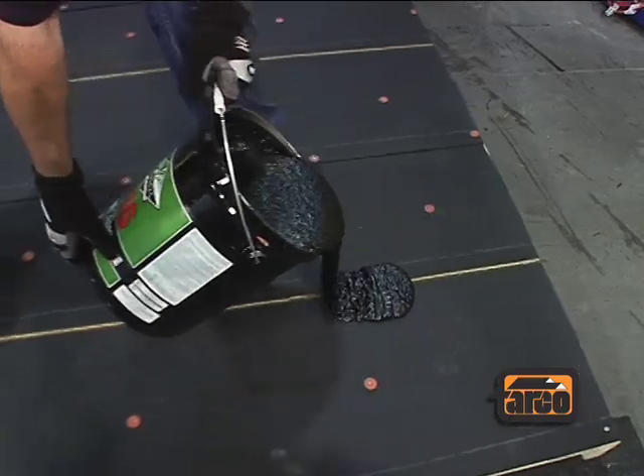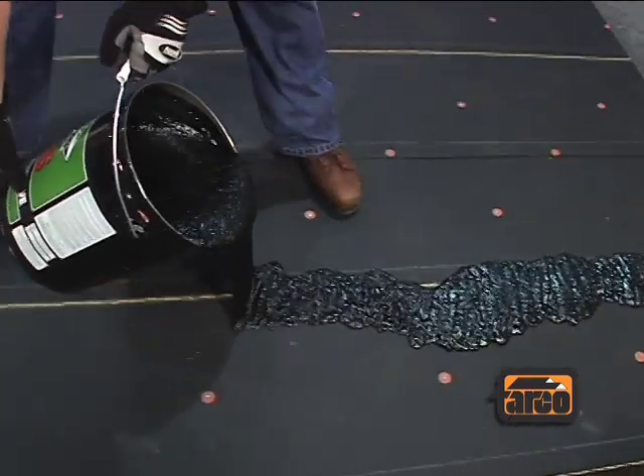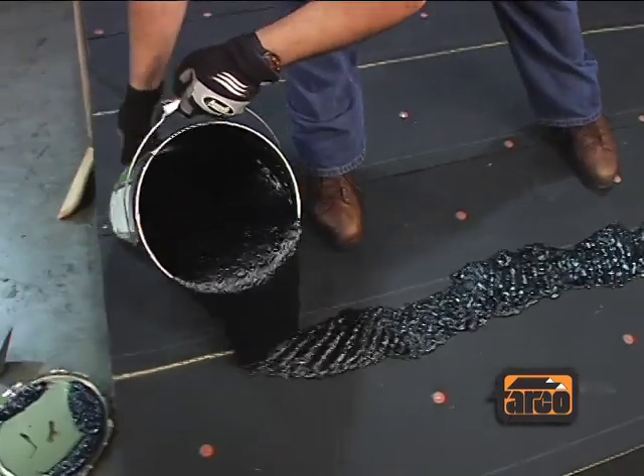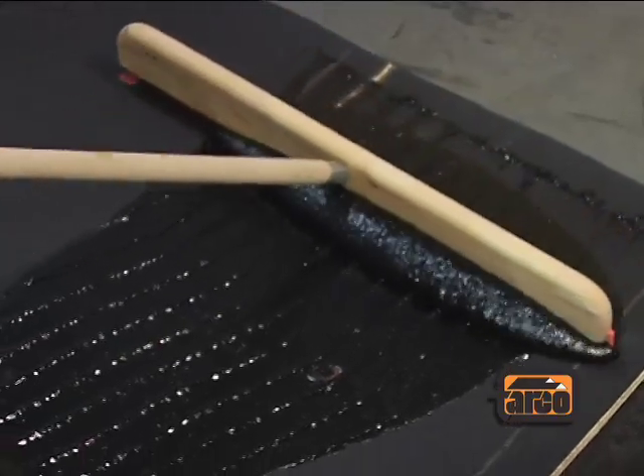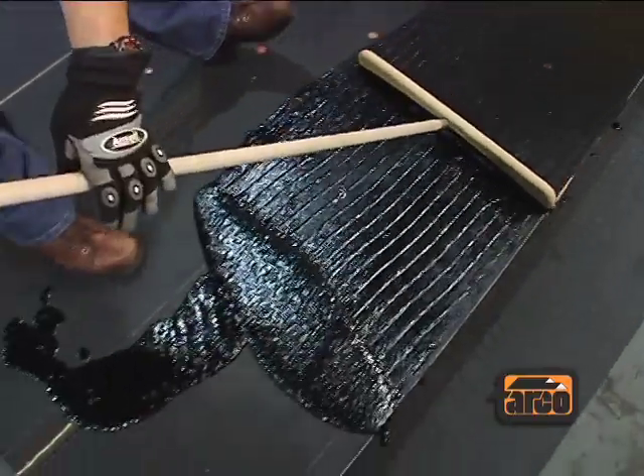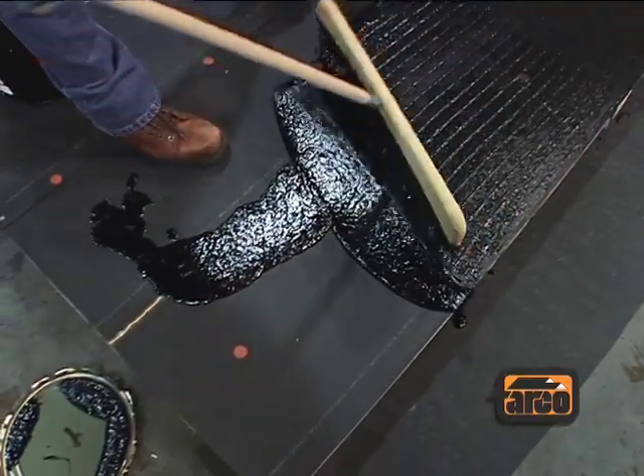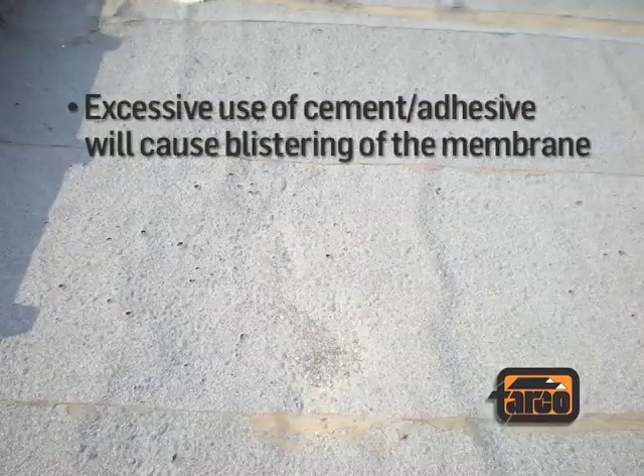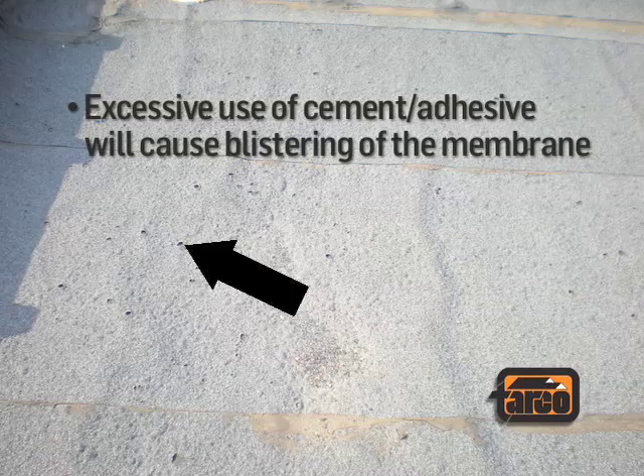Then install the Tarco MSR membrane using an asphalt-based, ASTM-compliant roof cement adhesive with a serrated trowel or squeegee in the amount necessary to obtain proper adhesion. Under no circumstances shall the adhesive quantity exceed the rate of application recommended by the adhesive manufacturer. Excessive use of cement or adhesive will cause blistering of the membrane.